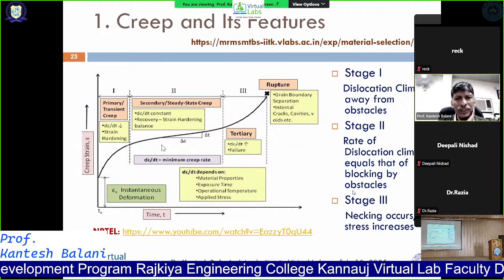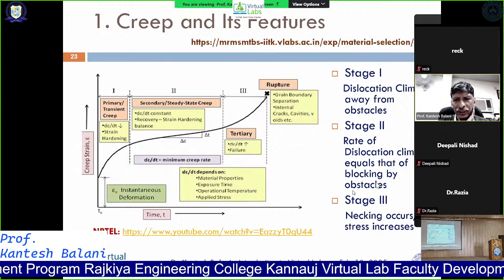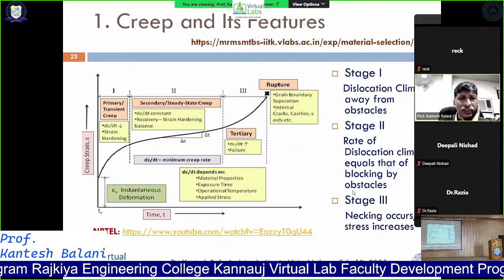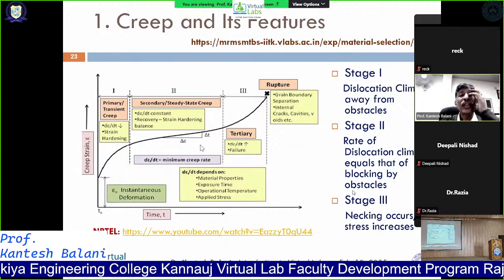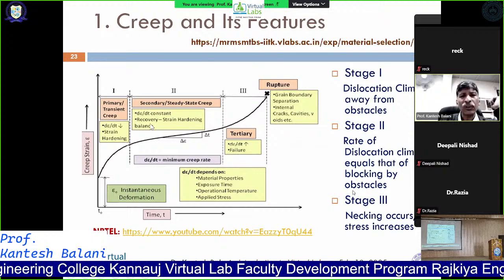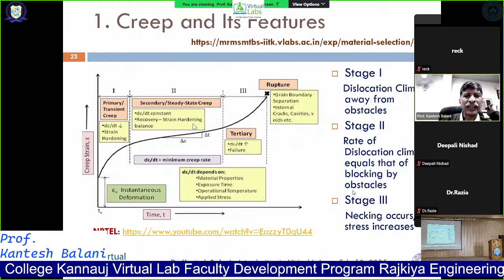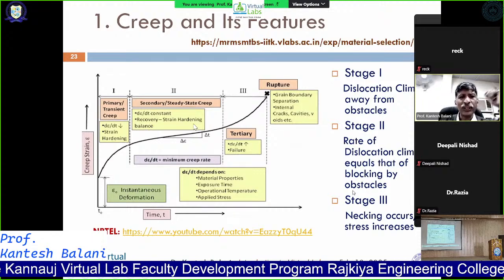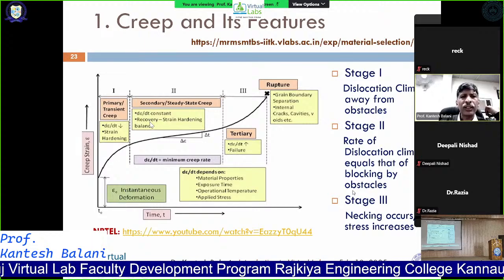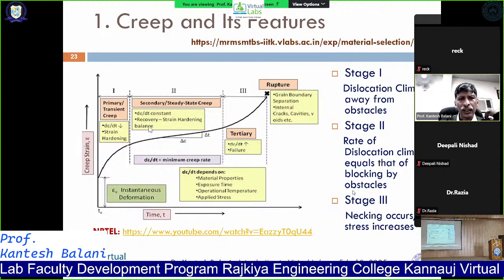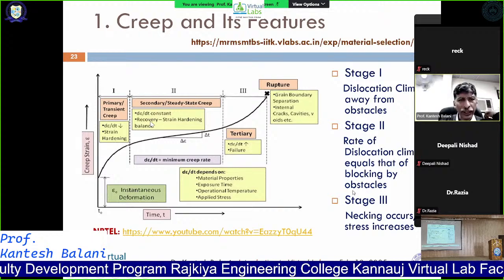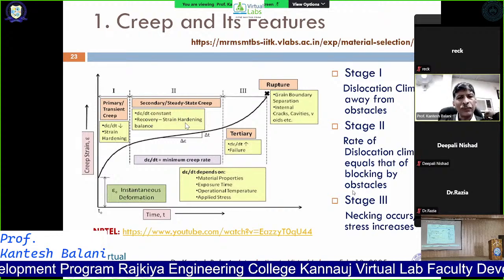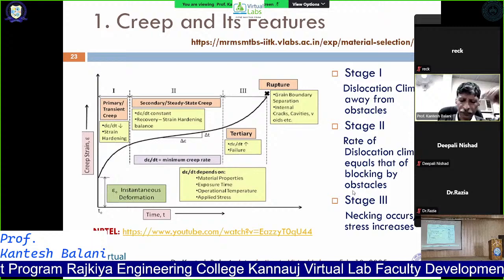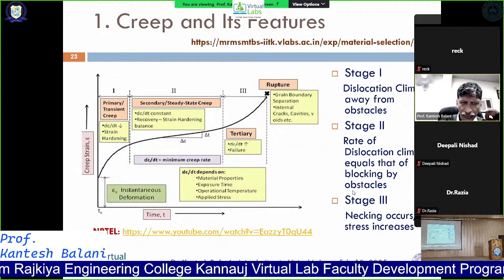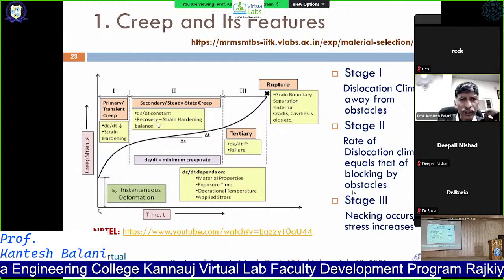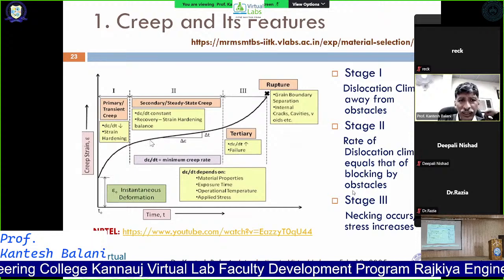And in stage 2, you can see there is a balance between dislocation climb or blocking by obstacles with respect to the strain hardening. So the material is hardening, and at the same time there is a sort of recovery in the system, and a deformation. So strain hardening and recovery start to balance one another. Recovery means how easily the dislocations are flowing and how easily the material gets hardened because of the deformation via dislocations. But anyhow, that is what is governing the lifetime of the material.